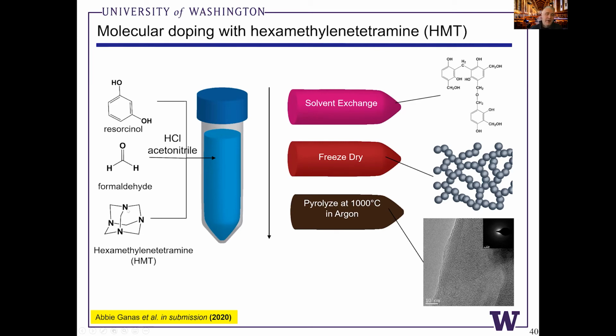And one hypothesis we were testing is, could we potentially dope this molecular precursor, like hexamethylene tetramine, and form B centers by preventing this molecule from dissociating enough, having 4 nitrogen atoms very close to each other at high pressure, high temperature conditions, and effectively convert to a B center. So the process is